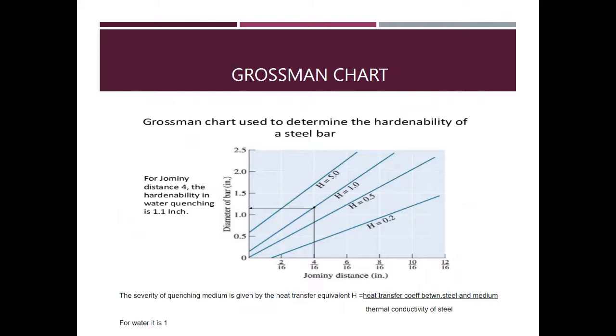Having determined the Jominy distance, we can now estimate the hardenability using the Grossmann chart. Here one more parameter is there. The severity of the quenching medium is given by the heat transfer equivalent H, which is the ratio of the heat transfer coefficient between steel and medium to the thermal conductivity of steel. Here for water, H is equal to 1.